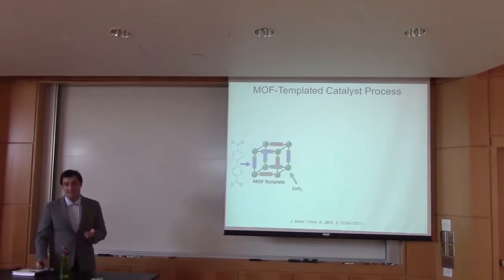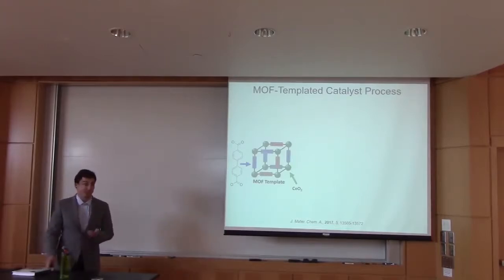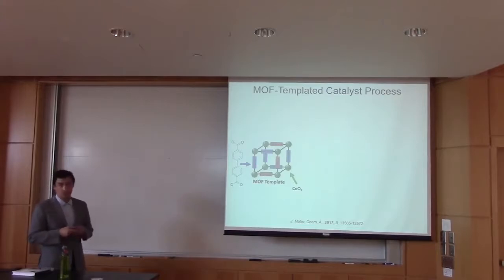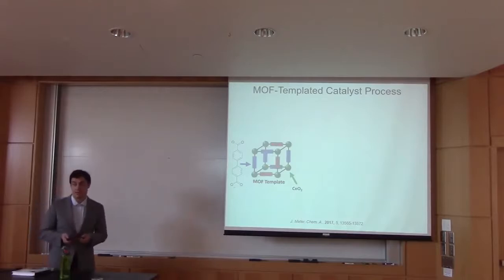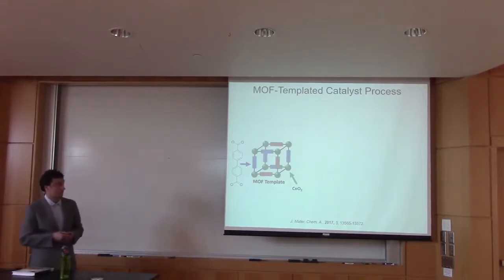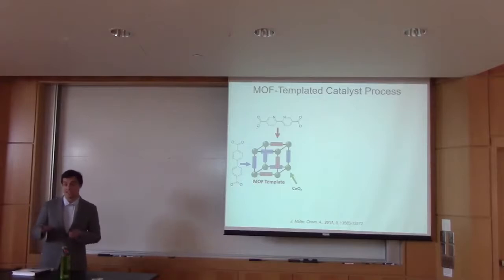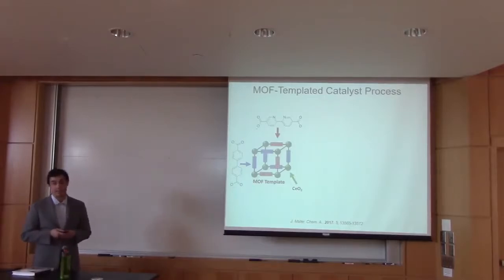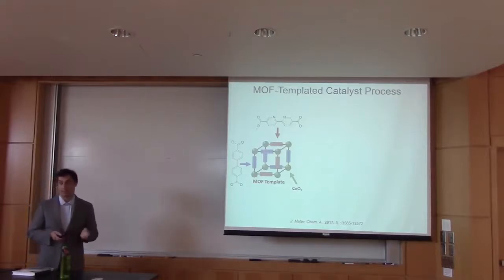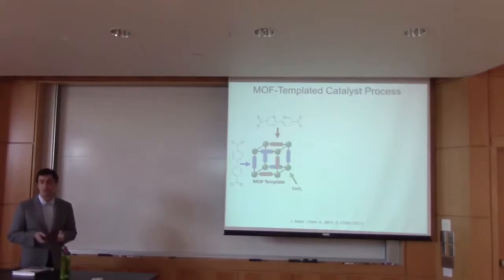Now, how we're doing this is through this MOF templating process, which is a mouthful, and I'll be saying it a lot. We're going back to our simple image of the MOF as a cube, and now every chemical and every molecule I refer to is going to be the one I actually use in my system. So these green spheres, the metal nodes, are going to be ceria or cerium oxide. These blue cylinders are the organic linking units, which are biphenyl dicarboxylate. And we can use and tune a secondary linking unit. Here I'm using bipyridine dicarboxylate, which is basically this, where we've swapped out 2 carbons for 2 nitrogens, which will give us different properties while still maintaining the same shape.